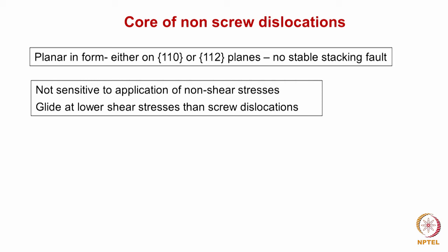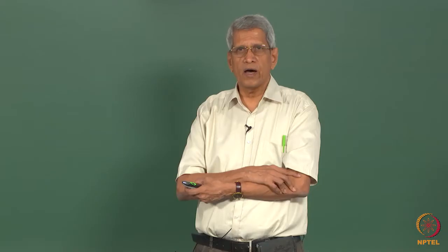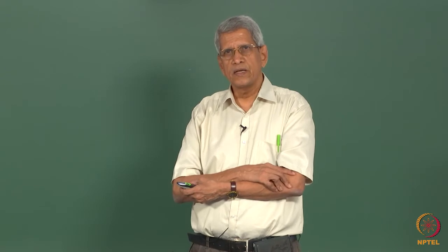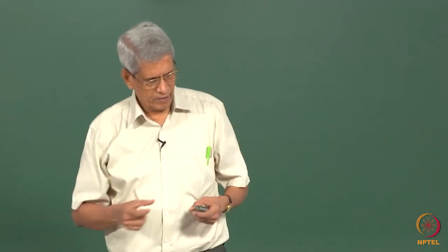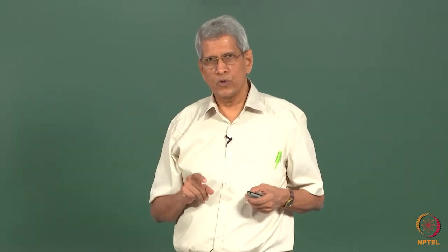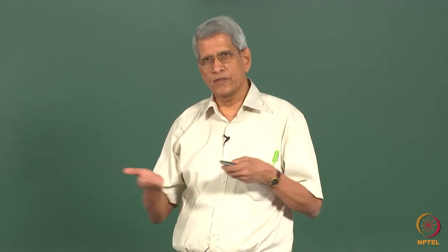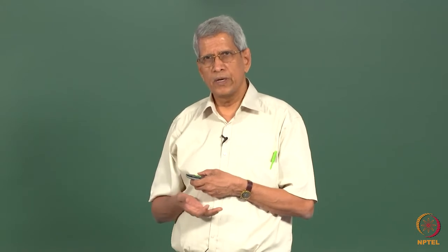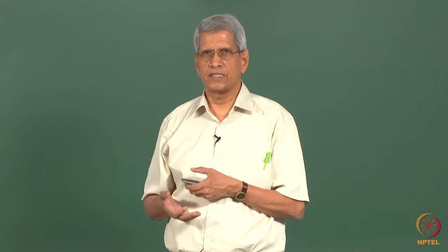And another observation is that in the case of FCC material, when we apply a shear stress for an edge dislocation, it's very sensitive to the application of not only the shear stress but non-shear stress components, like a tensile stress which we apply, and lot of vacancies will be generated because it will climb up or down. That sort of sensitiveness to a non-shear stress has not been observed for perfect dislocations in BCC material. And another observation is also that compared to screw dislocations, since the core is essentially confined to a slip plane, it's easy for them to move, and they move at very small shear stresses.